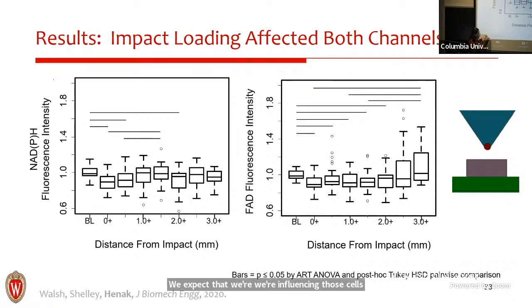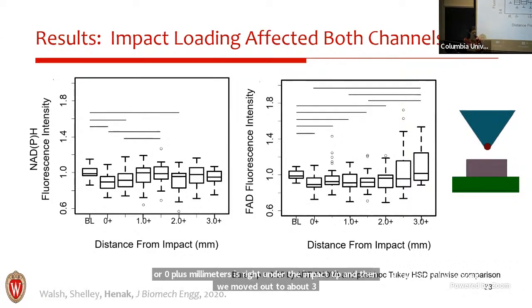Because we had this non-uniform strain field under the impact tip for this case, we also looked at the effect of distance from the impact. So we binned the experimental data where we've got our 0+ millimeters is right under the impact tip, and then we moved out to about 3 millimeters. This is a 6 millimeter diameter plug, so 3 millimeter radius.